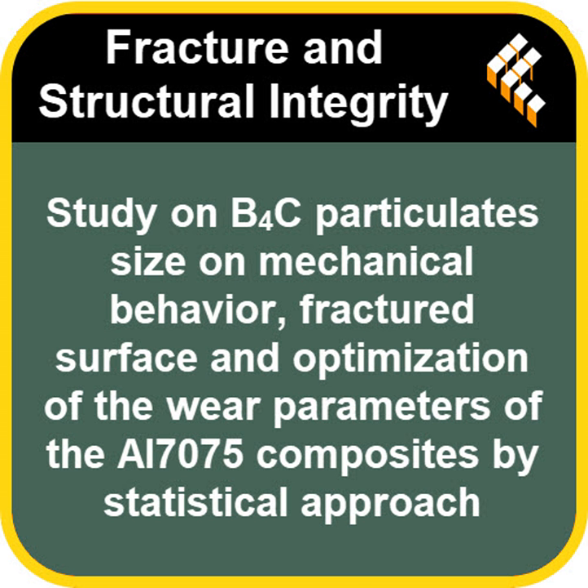Okay, what about porosity, those tiny voids or gaps within the material? That sounds like something you'd want to minimize. Definitely. Porosity is a critical factor for material integrity. And the key finding here was pretty clear. Nano-sized particles typically resulted in lower porosity. Lower porosity with nano, why is that? It's mainly their size. Because they're so small, they can disperse more effectively throughout the matrix and fill in the tiny spaces between the solidifying metal grains more efficiently. This leads to a denser composite with fewer voids, fewer potential weak spots.